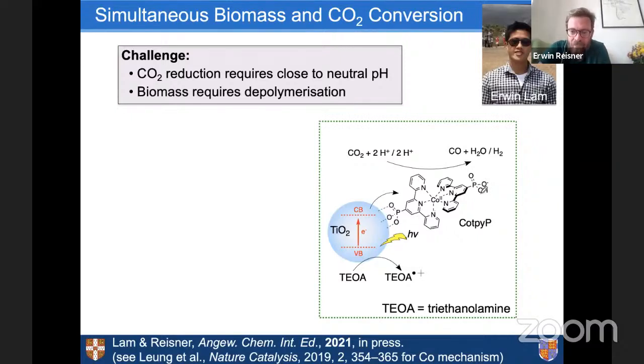If you wonder about the mechanism here, because this looks like a completely saturated cobalt center, what we believe, and we have a lot of evidence from spectroscopy, is that both terpyridines stay connected, and only one pyridine upon reduction opens up a vacant site. So one pyridine decoordinates, opens a vacant site for CO2 to come in and do the catalysis.